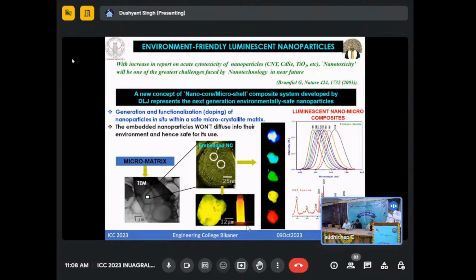You have got zinc sulfide material. When there are vacancies, it will give blue color. As you heat it, a shell layer of zinc oxide is created. As you heat it, the thickness of the layer increases. So if you start with blue color, and as you increase the temperature, you get to the red color. So again here, by varying the temperature.